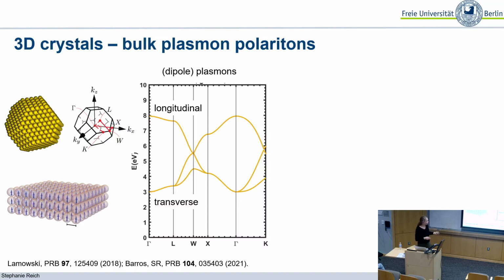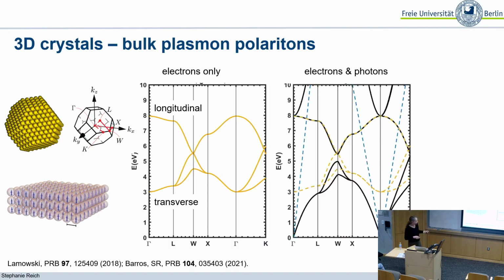Okay, let's put the photons in too. So now the dashed yellow is exactly the same dispersion as I had here. So these are only the plasmons or only the dipoles. And the dashed blue is the photon dispersion in free space. Nothing fancy with it. You can see that for the longitudinal mode, essentially nothing happens. And that's not surprising because photons are transverse excitations and they will not couple to a longitudinal excitation.